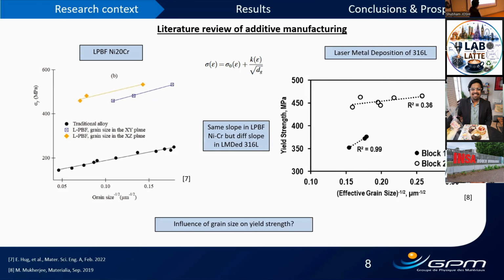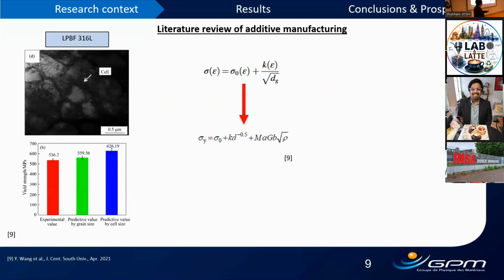But if we consider laser metal deposition of 316L, for the same kind of graph, yield stress versus inverse of square root of effective grain size, we see that the slope changes for differently fabricated samples of the same alloy. So that means there is an influence of grain size. So can we generalize here that it is associated with process parameters, or is it associated with process or material? Well, the question is still open.